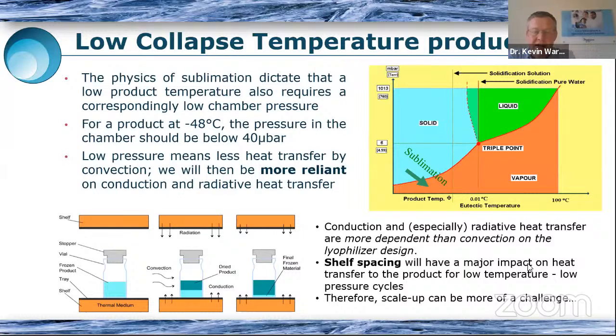And sometimes the vial is not as strong as the ice, which seems quite strange to think of, but we know that ice is extremely strong, and so that can be why that happens. Micro collapse, that's really interesting. 33% say micro collapse. So again, that's where the impedance analysis can be really helpful in showing you what is the lower of the critical temperatures associated with either the crystalline or amorphous part of the formulation. So that can give you an idea of what is a limiting factor that governs, I guess, the maximum product temperature, the critical temperature that you need to think about.